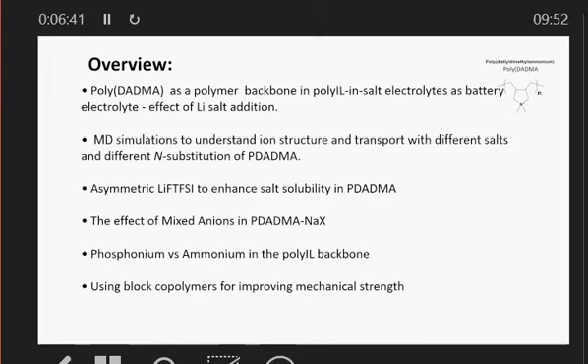I'm going to focus very much on a polymer, polyDADMA, which is a material that was introduced to us through David Mecerreyes. It's a material where the charge is actually on the backbone. Many of the previous polyionic liquid systems have the charge hanging off the backbone. And I think what we found is that when the charge is in the backbone, it can have very different properties, particularly in terms of electrochemical stability.